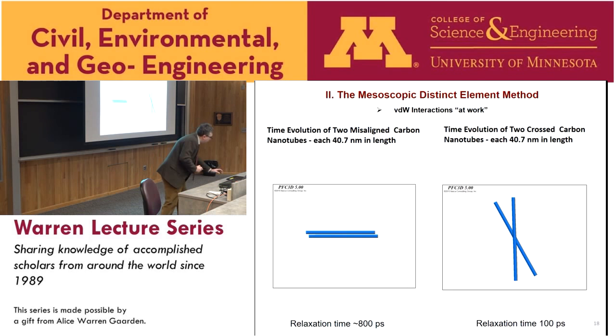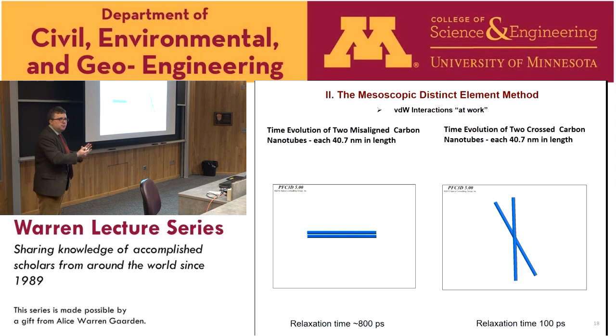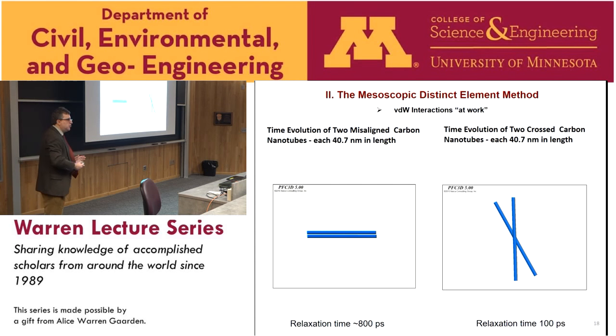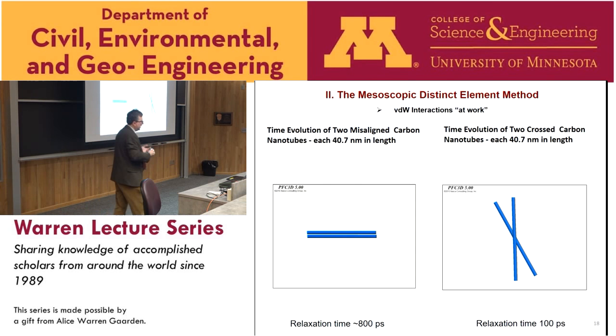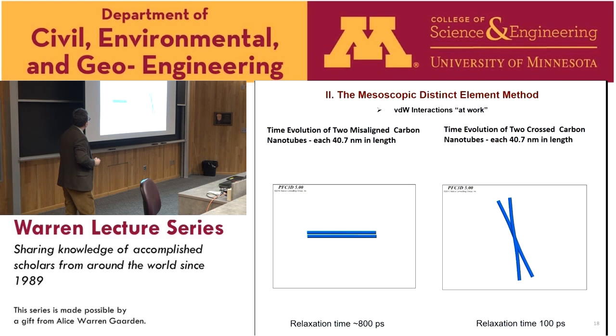We are matching the atomistic landscape of the interaction. The key is that at atomistic scale interactions depend only on distance R. If we used such an analytical form at the mesoscale, we would have artifacts — as we slide elements against each other with an isotropic potential, we get non-smooth behavior when elements are staggered. We correct this artifact by including the theta dependence — the misalignment dependence — so the potential is now smooth, as it is at the atomistic scale. Here is an example showing that with two misaligned tubes, they slide smoothly and prefer to align to maximize van der Waals attraction energy. With crossed tubes, the aligning moments do their job.